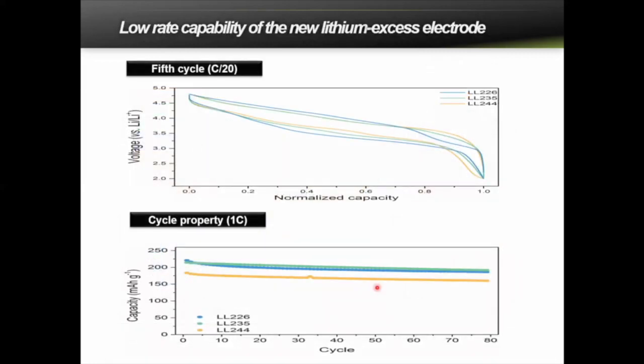And then we found out that, unfortunately, some other problem emerged with this new material. It showed a comparatively lower power capability. When it operates at slow charging rate, like C/20, which corresponds to about 20 hours of charging time, it was okay. But when it's charged at a practically important rate, like 1C, which is about 1 hour charging time, its capacity, 244 is our sample, is notably lower than the usual lithium excess material.